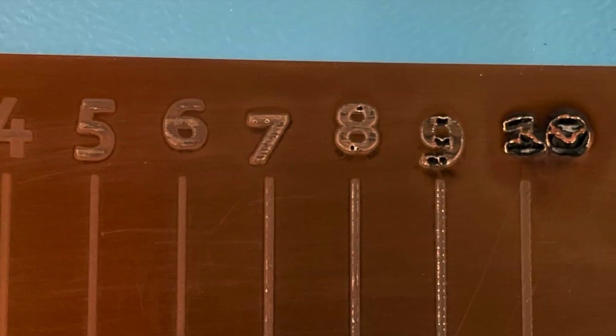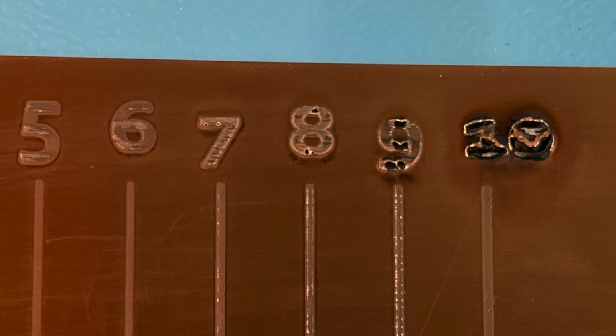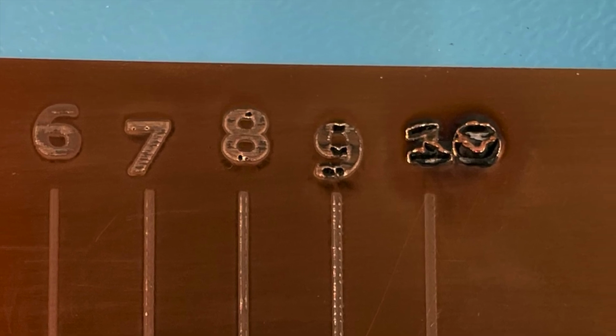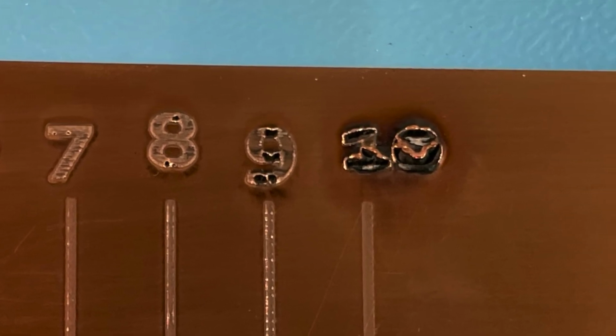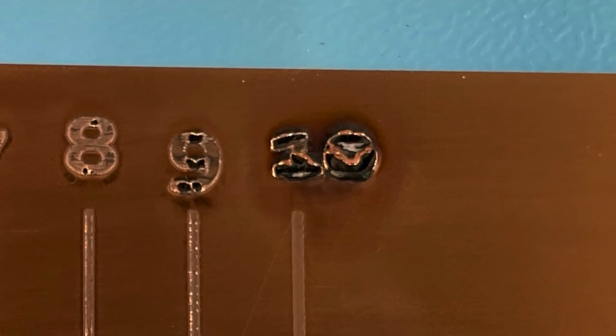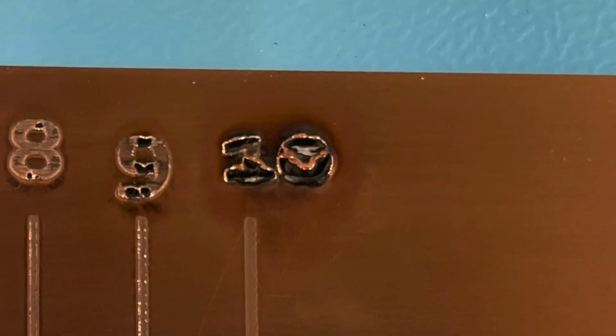If you know a little bit about lasers, you will know that melting through a material is basically not what a laser is supposed to do. You're basically aiming to evaporate, to burn the material right away, instead of heating it up so that it melts and then drips through the hole that it has just melted through the material. That's what happened here, not what we aimed for. It was simply because we had such a low speed on the laser that the heat could accumulate at one spot and therefore melt the whole material away. But never mind this little cosmetic mistake.